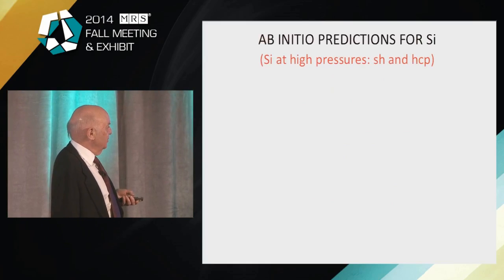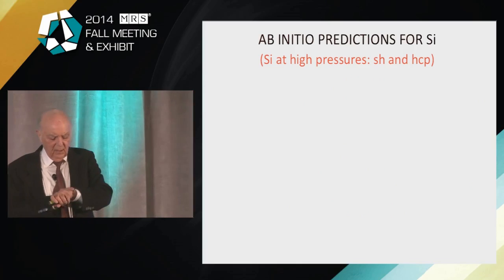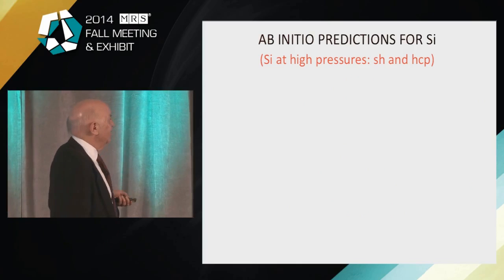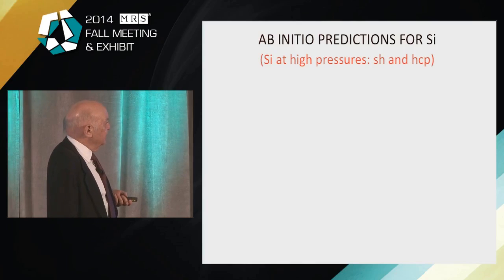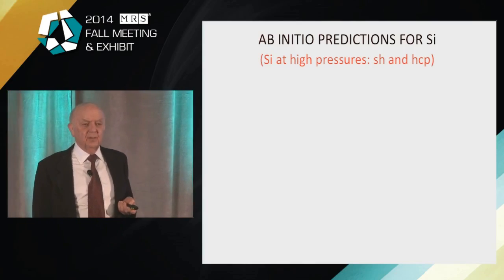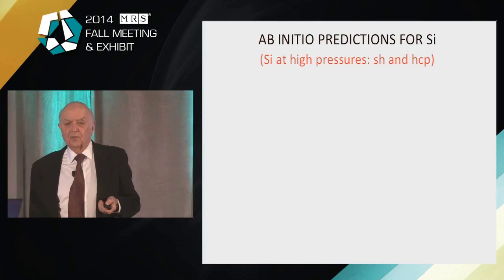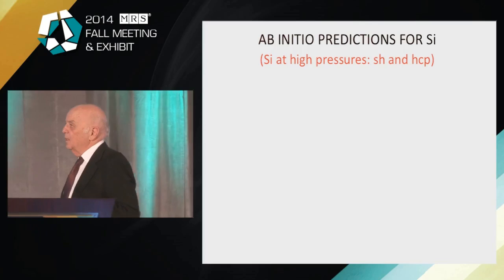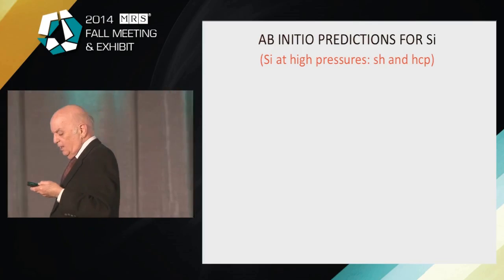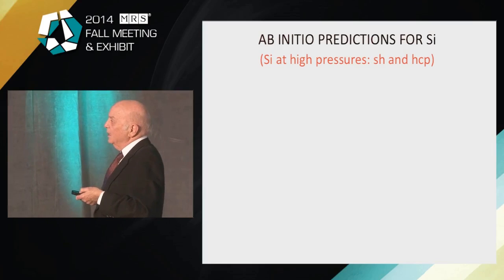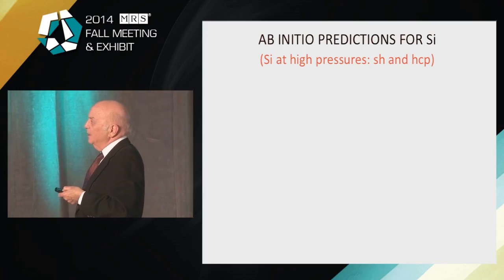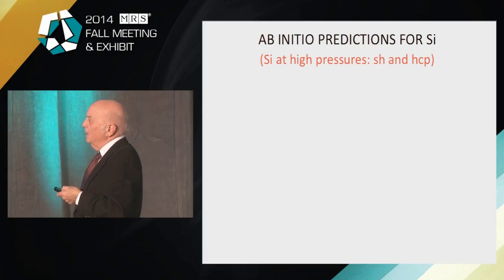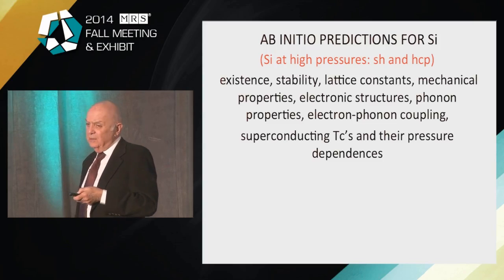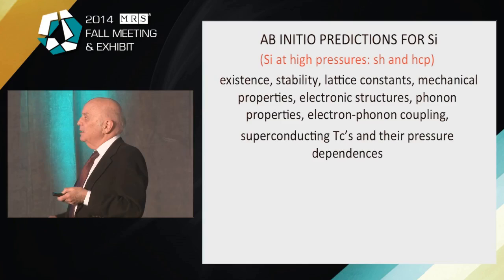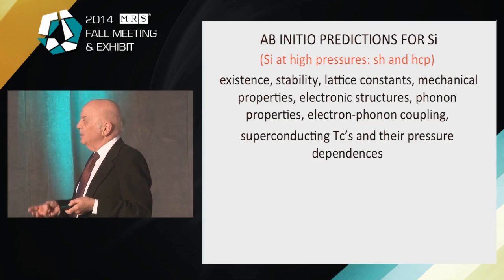So there's a bunch of materials, and I thought I'd just mention what we did with silicon, and then I'll come to the end of my talk. If you put silicon under pressure, it goes into many phases. As I mentioned, some of them could be useful for photovoltaics. But an example of some high-pressure phases of silicon that are metals is that if you put silicon under pressure, you can predict that there'll be a simple hexagonal phase that's a metal and a hexagonal close-packed phase that's a metal. You can predict the existence of these materials, their stability, the lattice constants, the mechanical properties, the electronic properties,